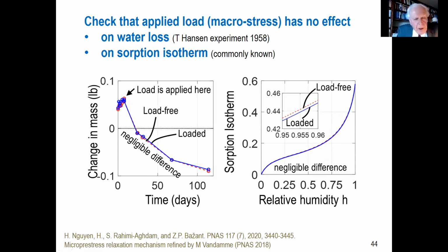Now, another thing to check, we know that external load cannot cause escape of water from concrete or cement paste. It was shown already by Hansen in Stockholm in 1958 that you have two specimens, one loaded, one not loaded, and both are drying. You cannot tell the difference. There is a negligible difference in calculation, but it cannot really be detected easily by measurements. So the model predicts no effect.